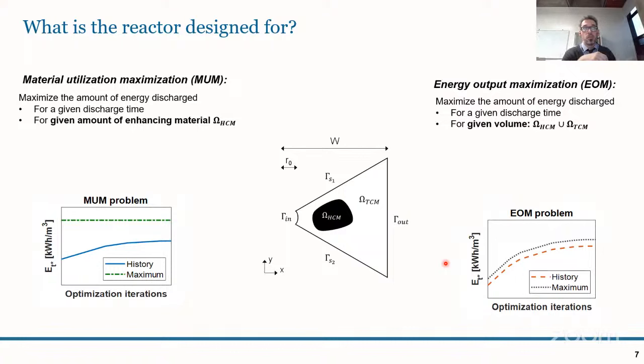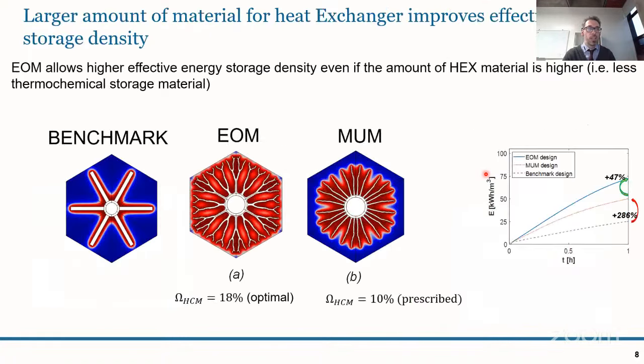One is what we call material utilization maximization. So this means the total amount of energy that can be retrieved from the thermal storage system for a certain amount of time and for a certain amount of volume dedicated to the heat exchanger. And the other is energy output maximization, where we only constrain the total volume occupied by both the material and the heat exchanger. And we look at effective energy storage density, which means the energy retrieved above a certain temperature threshold, because of the quality of the thermal energy.